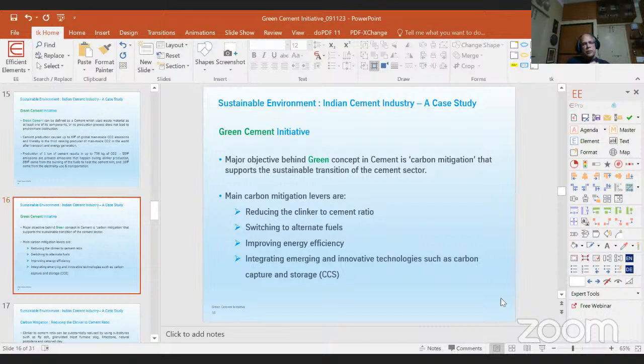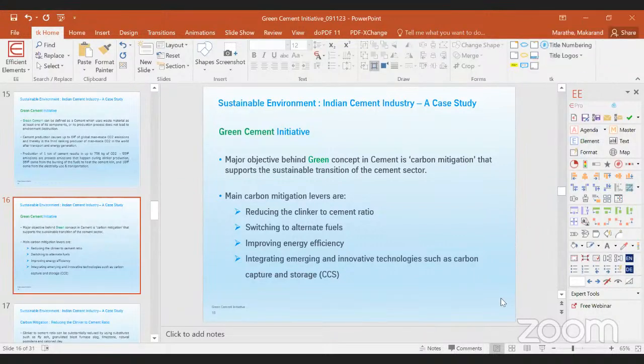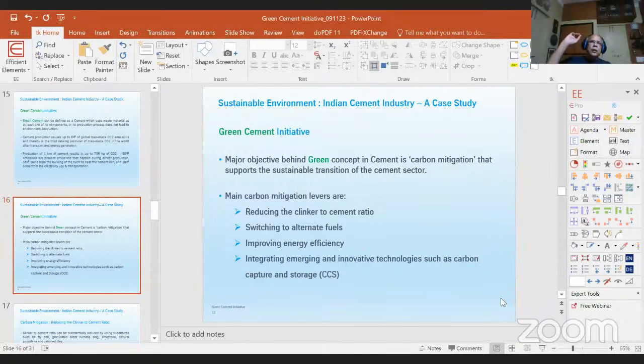So, reducing the clinker to cement ratio, switching to alternate fuels. As I mentioned, 35% of the CO2 emission is coming from fuel. So shift to alternate fuels, which will reduce the CO2 emissions. Improve your energy efficiency. Now, energy efficiency improvement will be an indirect reduction in carbon footprint. If you improve the energy efficiency, your consumption of grid power will reduce. Naturally, the generation, the fossil fuel utilization, also will reduce, and indirectly it will reduce the carbon footprint.